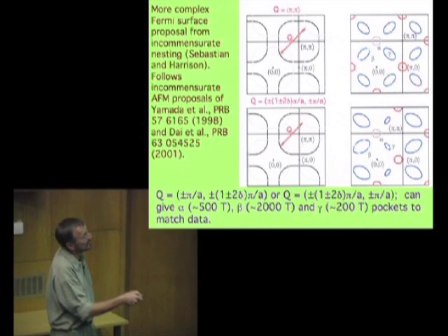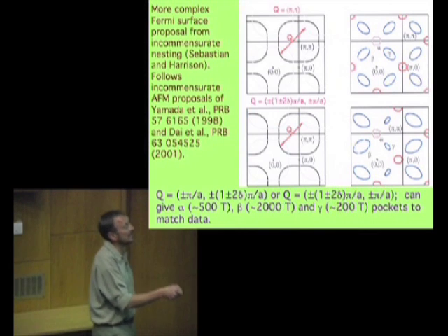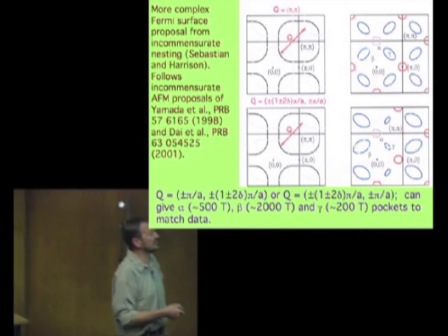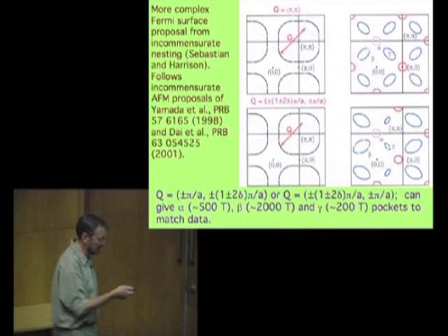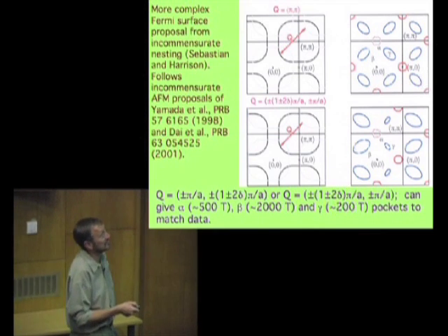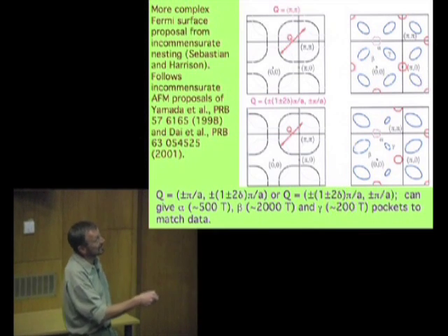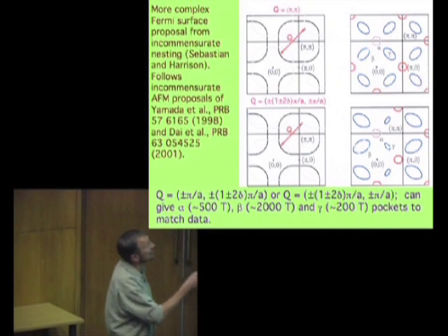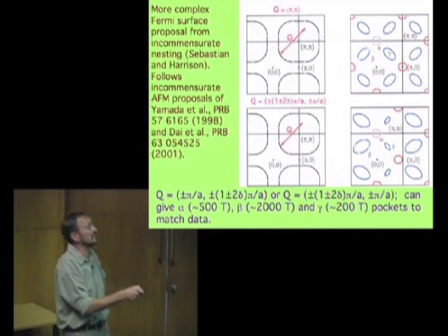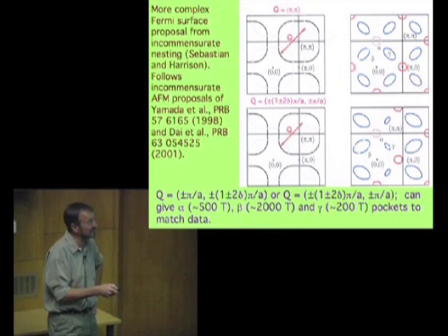And these pockets match up with our data very well in size. They also, again, give you a good calculation of the electronic specific heat. So this is our best guess, based on the data from neutron scattering and from our Fermi surface measurements, as to what the Fermi surface of the cuprates actually looks like.